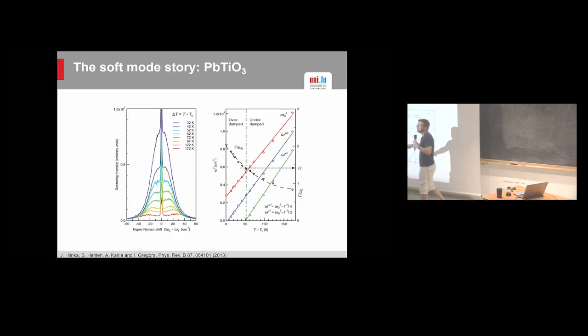That's okay. But it still allowed them in this paper to make very nice fits off of the soft mode behavior. And then you will find this discussion on how the damping changes across TC and so on. Not going too far into the physics, but this is really to highlight this measurement because to me it's one of the very, very beautiful determinations of soft modes above TC in lead titanate.